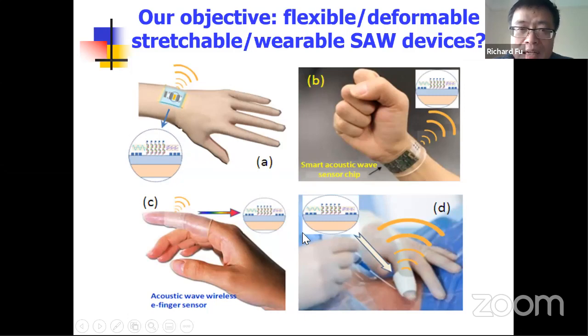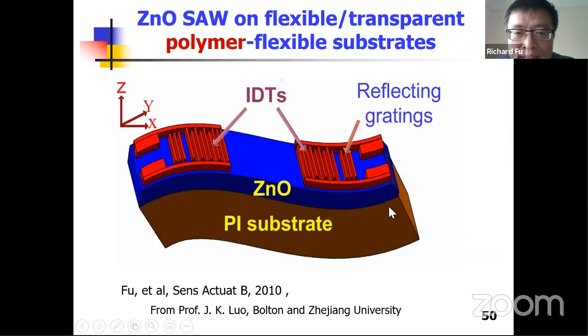For recent work, we are actually doing a flexible, wearable device. We want to demonstrate that a SAW device can be used for wearable applications. For wearable applications, people always think first of polymer structures. Polymer is very soft and bendable. If we deposit a film, we can make the electrode and then make a SAW device. But polymer is soft and the energy is dissipated too much. Then the wave doesn't propagate very far, so for microfluidics functions, it does not work very well.